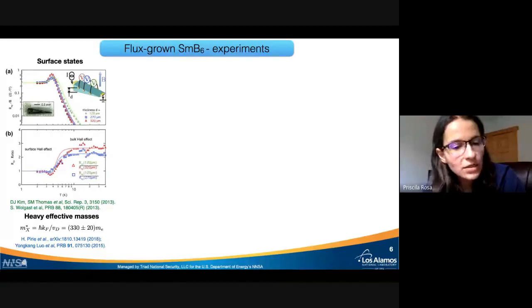The first one shows that the effective mass of the surface states is heavy, and that is shown by quasi-particle interference and scanning tunneling microscopy. And the second paper is through thermal power measurements. So they both agree that the masses are heavy. And again, this is consistent with the original prediction of a correlated topological insulating state.